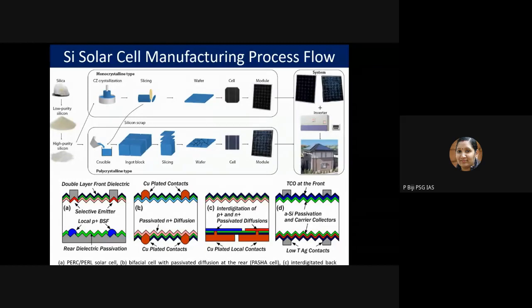The round ingot is cut with a diamond wire into very thin slices of square wafers. Then the wafers are coated with a thin layer of either P or N type silicon to form the PN junction. So that's the solar cell. After that, we need the anti-reflective coatings. The anti-reflective coatings are deposited, and further the metallic fingers, because the current collection has to happen, so you need the metallization. The metallic fingers are deposited on the top, and the rear contact is fabricated after that. Then flat ribbon busbars are added. That's how the solar module is manufactured in the industry, and it will be further integrated with the inverter, and it can be used for either domestic or industrial applications.